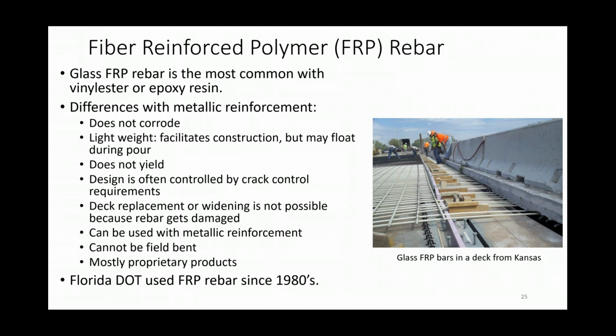These bars do not yield, so they essentially are elastic and then they fracture. So because of that, design is very different. And the design is often controlled by crack control requirements, because the glass FRP is essentially not as stiff as our steel bars. So crack control usually controls design.